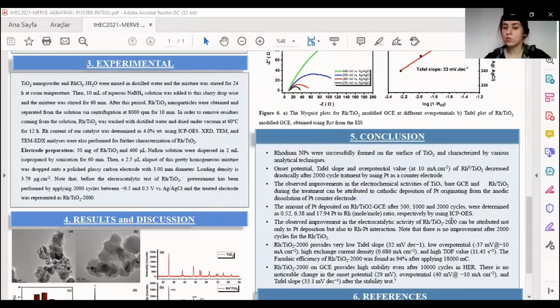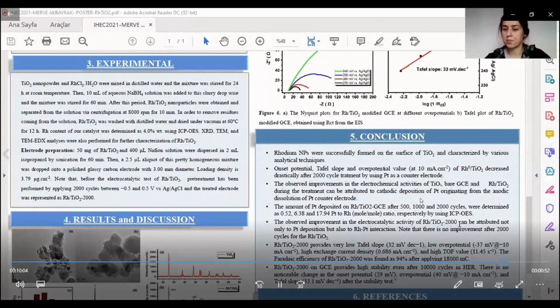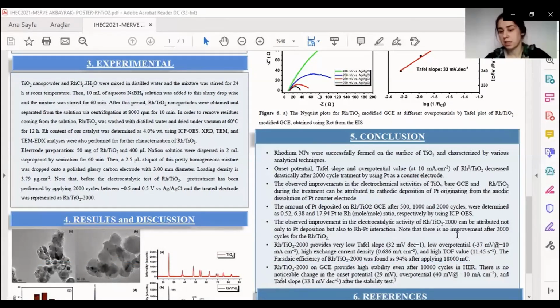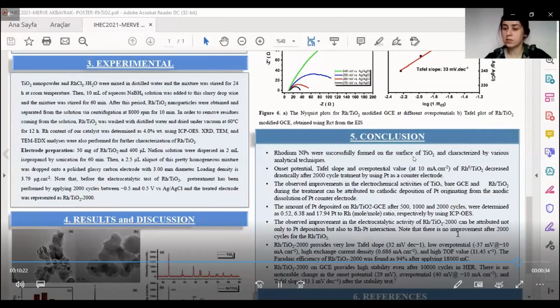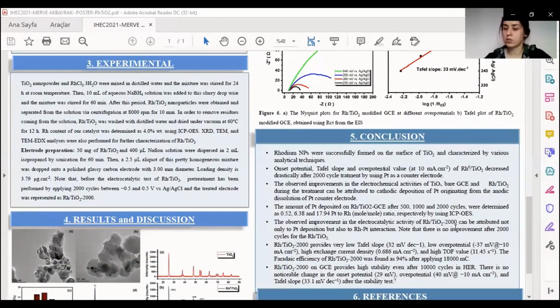Rhodium titania 2000 provides very low Tafel slope, 32 millivolt per decade, low overpotential, minus 37 millivolt at minus 10 milliamp per centimeter square, high exchange current density, 0.686 milliamp per centimeter square, and high turnover frequency values. The faradaic efficiency of rhodium titania 2000 was found to be 94% after applying 18,000 millicoulomb. Rhodium titania 2000 on glassy carbon electrode provides high stability even after 10,000 cycles in the hydrogen evolution reaction.